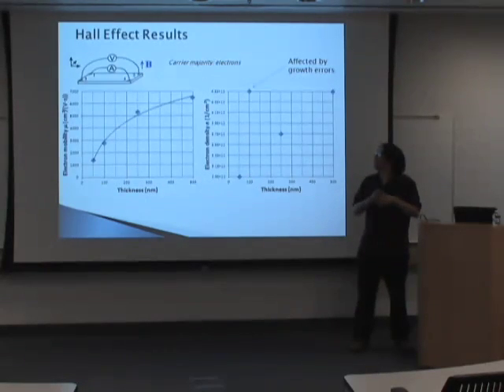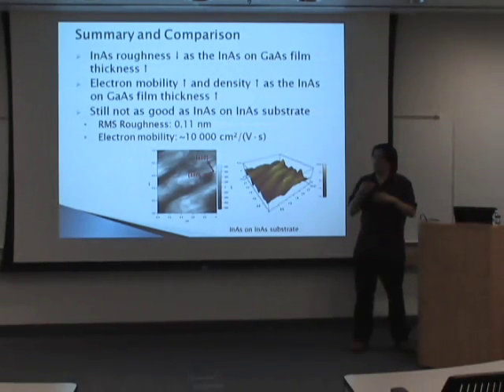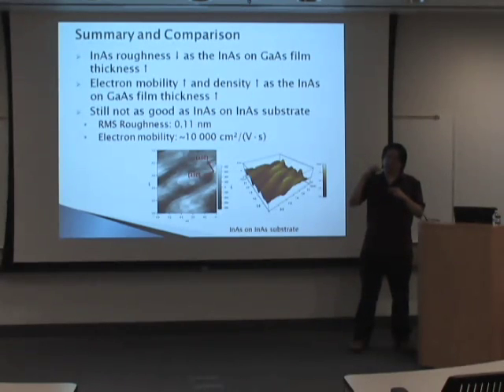And as for the performance, we saw some great results. We saw that the electron mobility went up as thickness goes up, but it doesn't make too much sense to just constantly grow indium arsenide on it, because that number eventually plateaus. And we did see the electron density go up as well. The anomalous 100 nanometer sample also showed that correlation. So from this data, we could at least begin to say that thickness has the following effects on indium arsenide grown on gallium arsenide: as thickness increases, roughness goes down, electron mobility goes up, and so does the electron density.